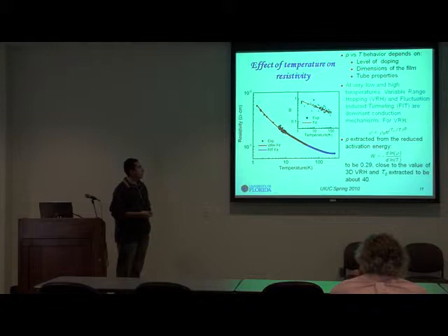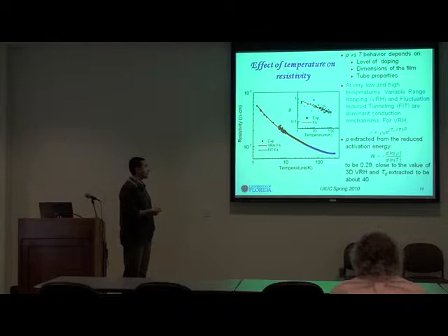It's not very strong, but it's quite not metallic behavior also that you expect, something like staying at the same level. So we could explain this data by a variable range hopping theory and fluctuation induced tunneling at different ranges of temperature. At lower temperature, it's basically dominated by variable range hopping, following an equation like this, for example. And here, the exponent p can be extracted from something called reduced activation energy, defined by this equation and plotted